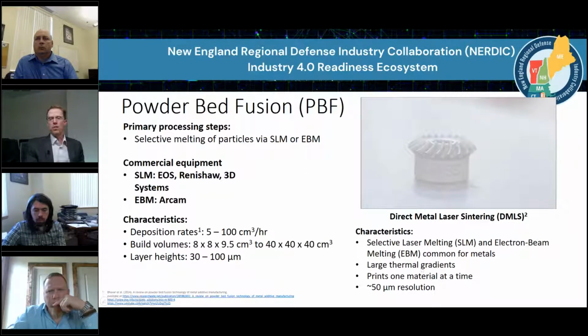One important thing with this process is that you get large thermal gradients. As you have a solid at the lower levels, you place a powder, and then liquefy and solidify on top as it cools. That leads to very large thermal gradients, which can lead to residual stresses and texturing.